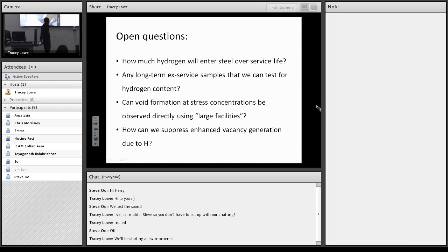Yeah, I can tell you, is there evidence? I've done some work, I haven't done this with, and maybe this is a really interesting experiment with charged samples. We did some work on biaxial stress state and corrosion fatigue. And we found in air, if you have a negative biaxial stress state, yes, the crack gets closed up, the fatigue lifetime is extended, as you might expect. You do this in corrosion fatigue, and it doesn't matter what the biaxial stress state is because the corrosion dominates the early stages. Now, doing this with hydrogen, where we're not actually pitting, yeah, that was the point. Maybe.